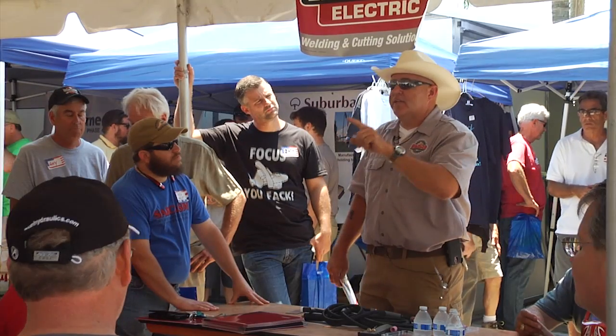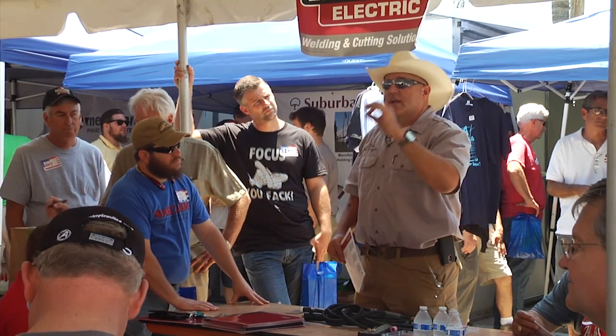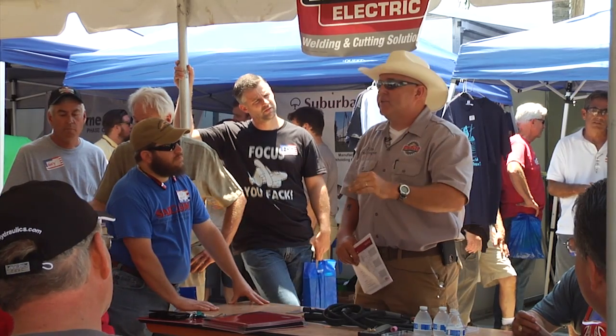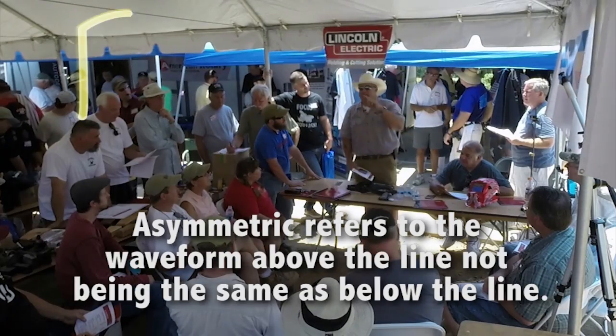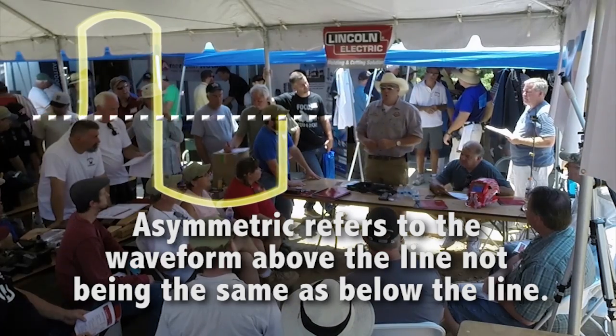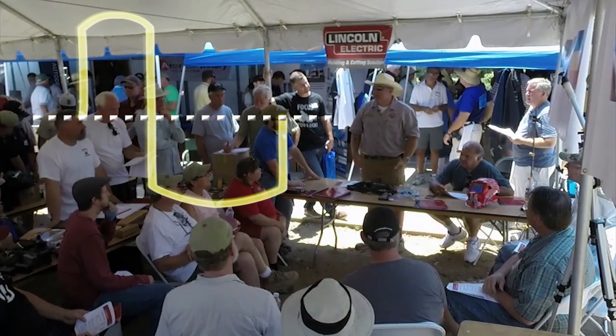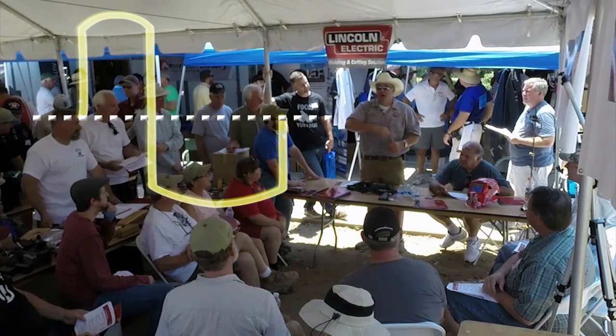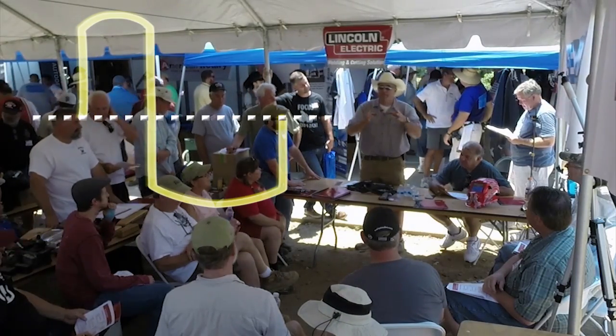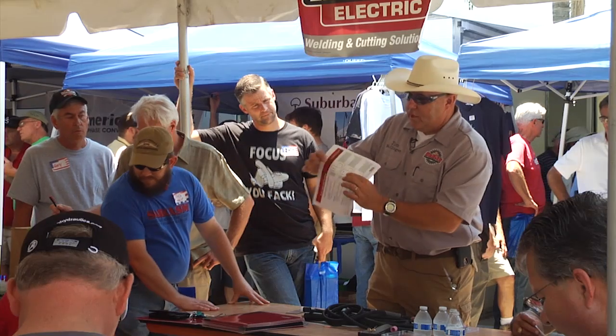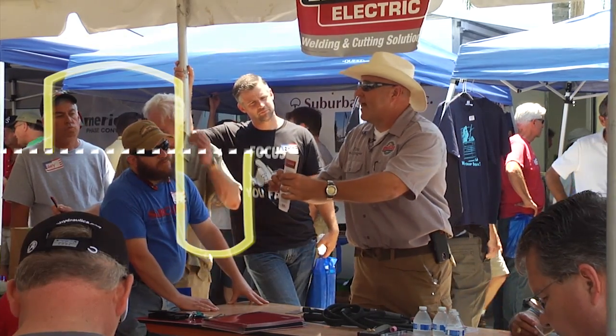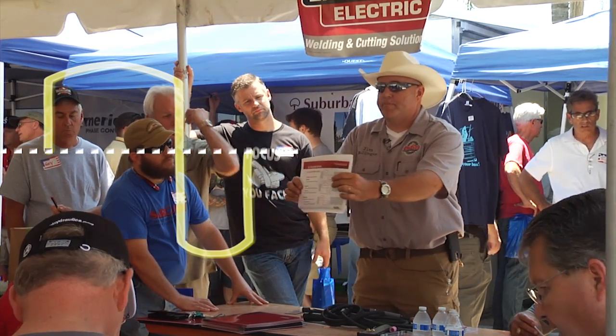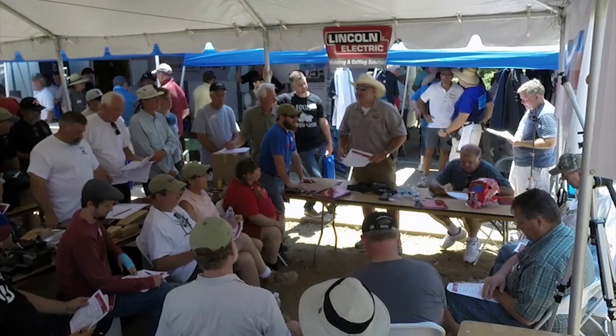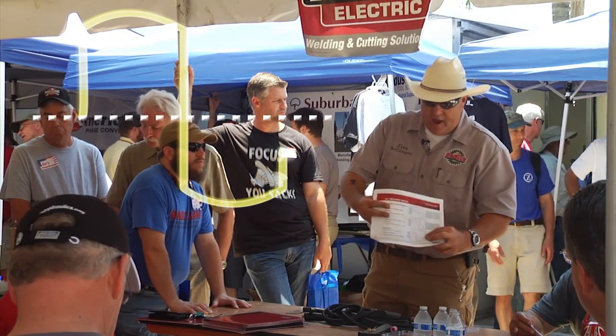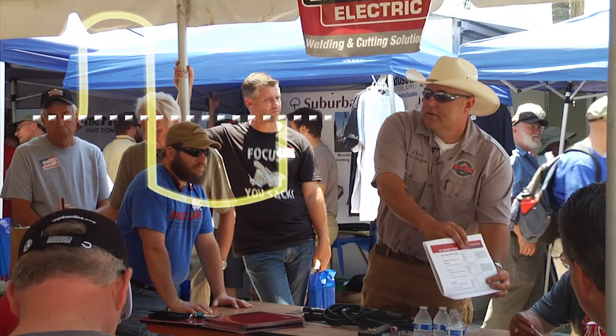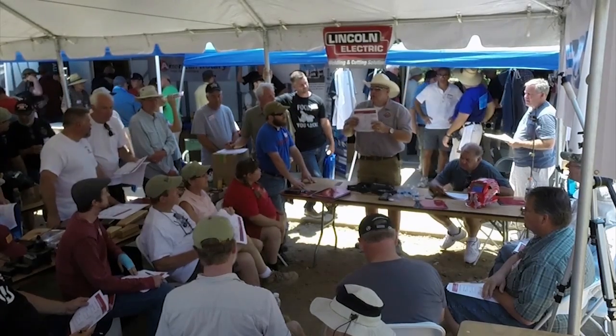But we now have machines, if you saw my Square Wave 200 video, I talk about it's an asymmetric TIG machine, meaning that now with technology, we can take that sine wave and we can manipulate it. We don't have to be positive as much as we're negative, because all we need is that sine wave to punch the oxide layer off. We can now take and shift some of that time down in the negative side. Look at the second one down. You see how that one's more positive? We're more time positive there? That means we're doing more cleaning. Look at the bottom one. We're now more negative. You see that? Right? So now we're doing more work.